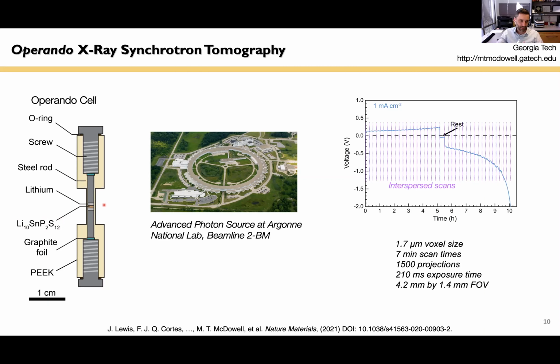And because we've optimized it in various ways, we can actually take this cell, put it into the beamline, and then do X-ray tomography on the cell while we're operating it. And that's shown over here. So this is the electrochemical data where we apply current in one direction, then we reverse the current in the opposite direction to cause deposition and then stripping. And these purple vertical lines are interspersed tomography scans.